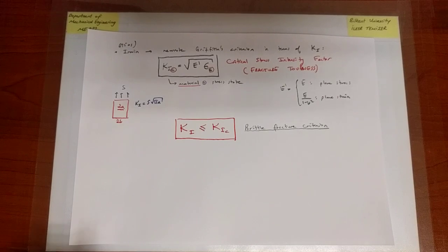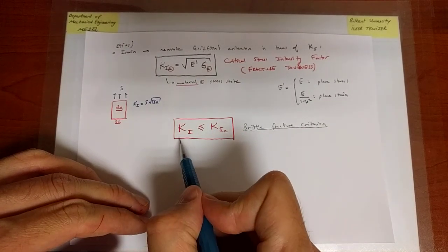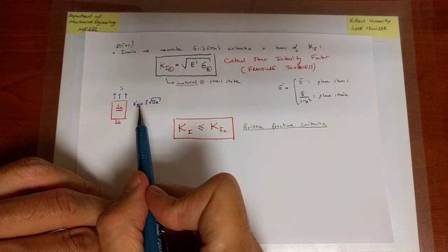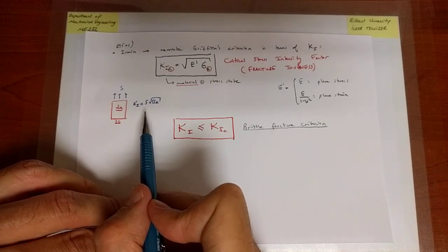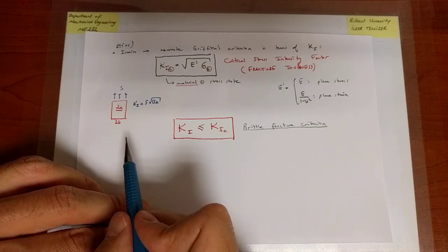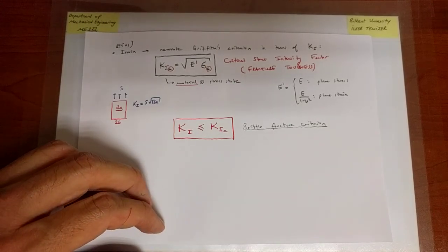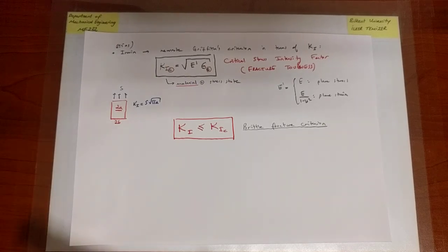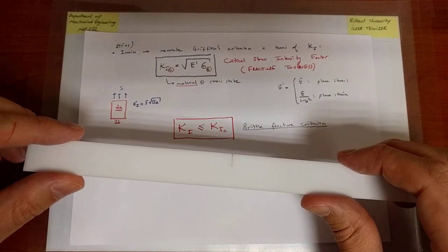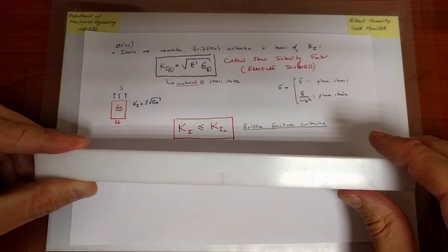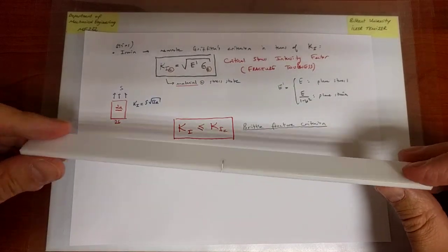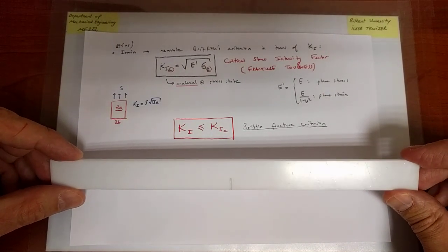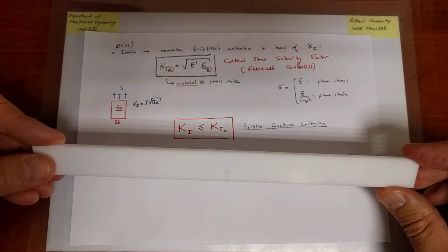Okay, so that is our brittle fracture criterion that we need to know by heart, just like we need to know the expression of K1. This, I should note at this stage, is a simplified expression for the stress intensity factor. We're going to build up upon that. Okay, now having said all of this, let us demonstrate what we have with a simple experiment. What we are saying is, first, the presence of the cracks is very important in a structure. So what I have here is a specimen that you are going to actually use in the experiment that I have just mentioned in the lab. And we have put a crack in it of a certain size, and we're going to load the structure.